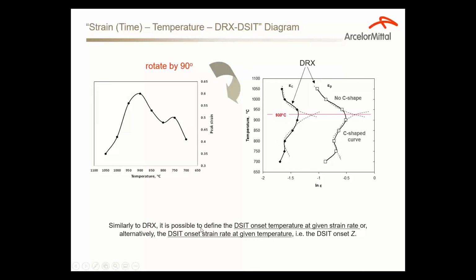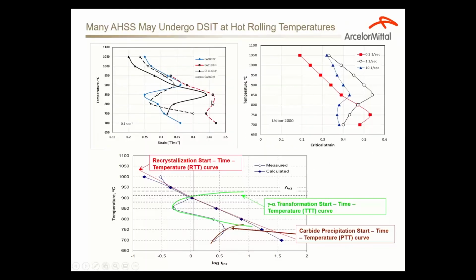And we can derive, similar to dynamic recrystallization, the transformation onset temperature at a given strain rate, or the transformation onset strain rate at a given temperature. So we can provide the mill with information on whether the transformation is going to happen during rolling. What is the transition range? What kind of temperatures they should be careful about, and so forth. This slide just illustrates how the strain rate affects the transformation, or how different grades can be transformed during deformation.